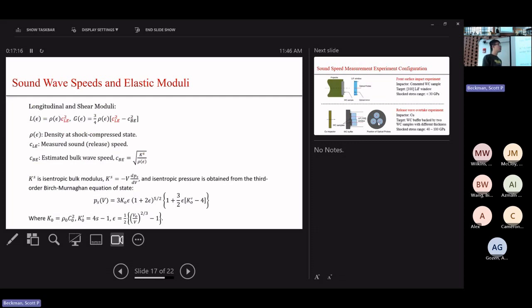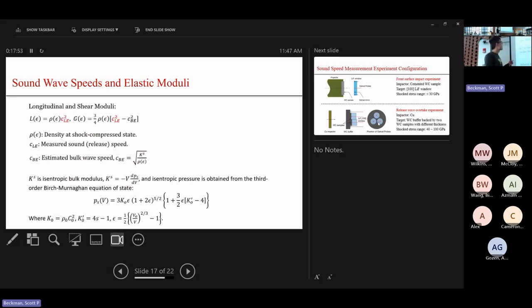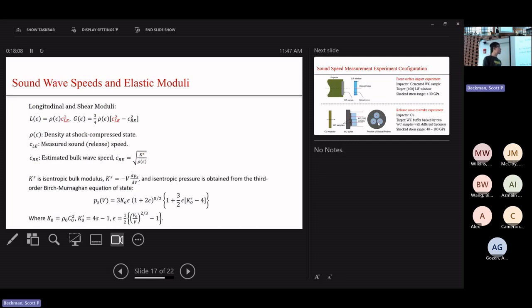The information we're obtaining is the elastic moduli — both longitudinal and shear moduli. By comparing the experimentally obtained longitudinal and shear moduli to values from theoretical models that assume no damage, we can quantify the state of damage in the material. CLE is the measured longitudinal sound speed, and CBE is the estimated bulk sound speed using the isentropic bulk modulus.